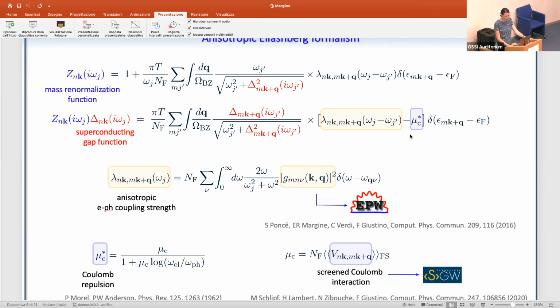So one limitation that I should point out in EPW is that we are still using a semi-empirical parameter for mu star. In a number of studies, we have calculated this using the screened Coulomb interaction with Sternheimer GW. In fact, Christoph has done quite a number of studies, I think, on hydrides. And I know that Antonio has done a lot of calculations recently estimating mu star ab initio, and for most phonon-mediated superconductors, mu star falls within the 0.1 to 0.2 range.